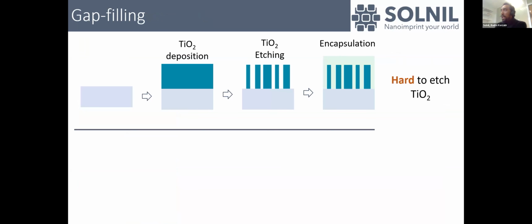That is key. So far, what we've shown is the standard approach to make metasurfaces. Basically, you start with a thick layer of the high refractive index material, you etch it, and then you do the encapsulation. One of the challenges that a lot of customers have today with etching TiO2 is that it's a difficult material to etch. So they have to come up with very slow etching processes. Sometimes they use atomic layer etching, which is quite slow.